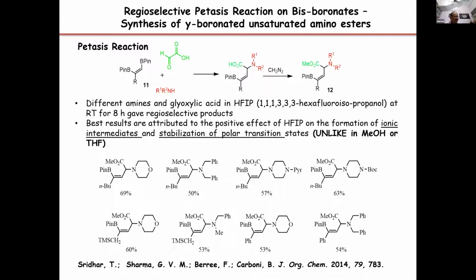Having seen the literature and reactivity of these systems, we initiated our work. Firstly, by the synthesis of a variety of bisboronate esters, and these bisboronate esters were subjected to Petasis reaction using glyoxylic acid and different amines to get the acid. The acid was then in situ converted to methyl ester on treatment with diazomethane.